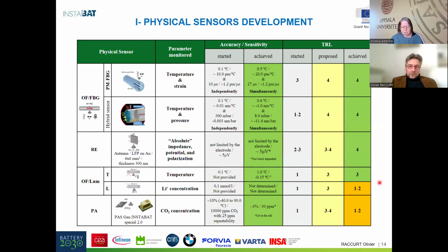In this table, I give you an overview of the results from each sensor, with the accuracy and also the TRL that we achieved during the project. We show that for the major part of the sensors, we achieved good results with a good TRL, but for the lithium sensor and the CO2 sensor, the achievement is not sufficient to be used in the battery at this time, and we need more research effort for these kinds of sensors.